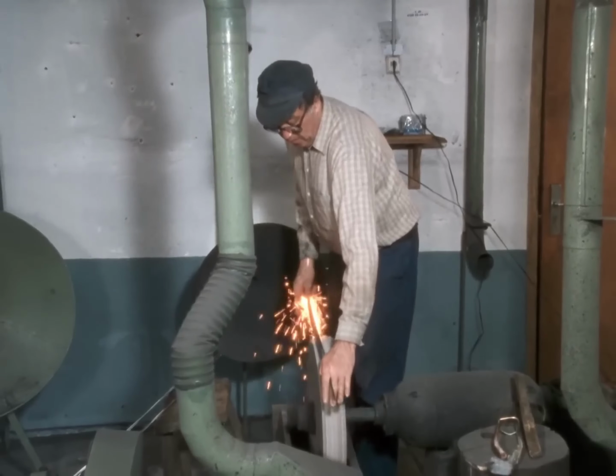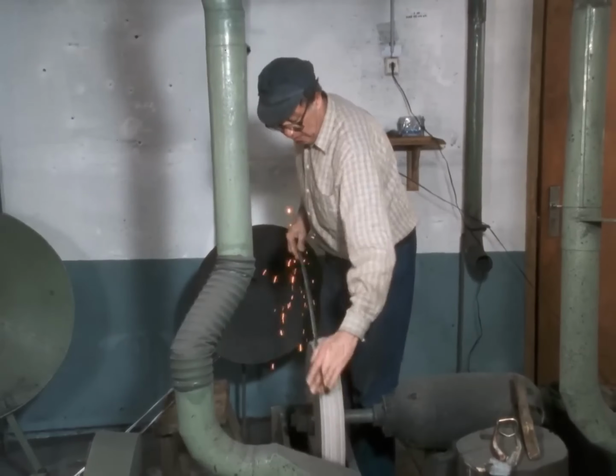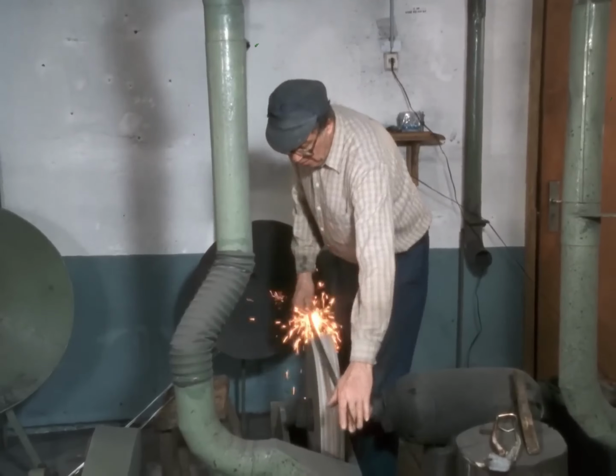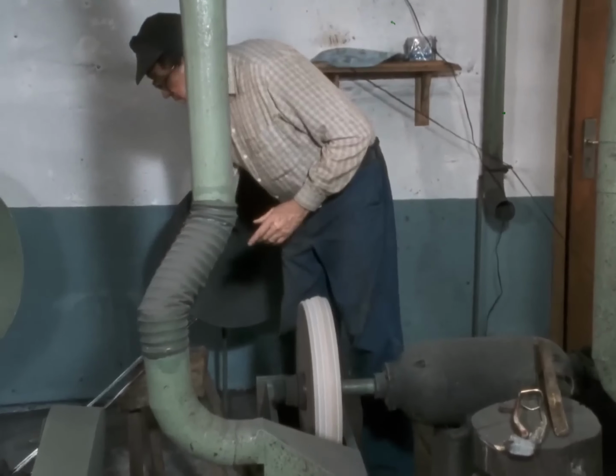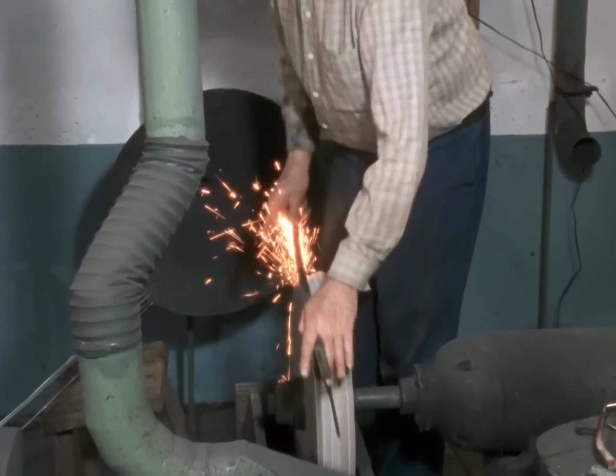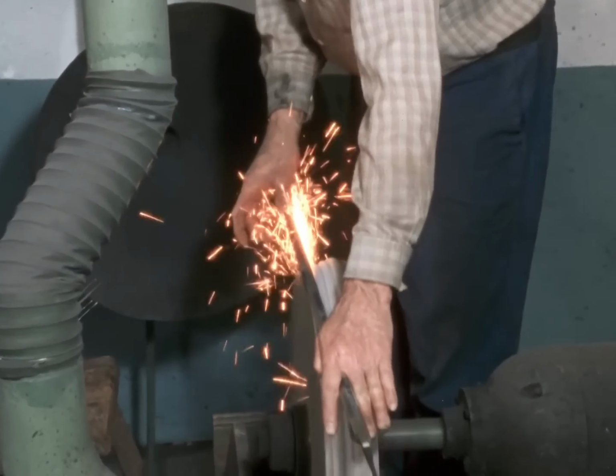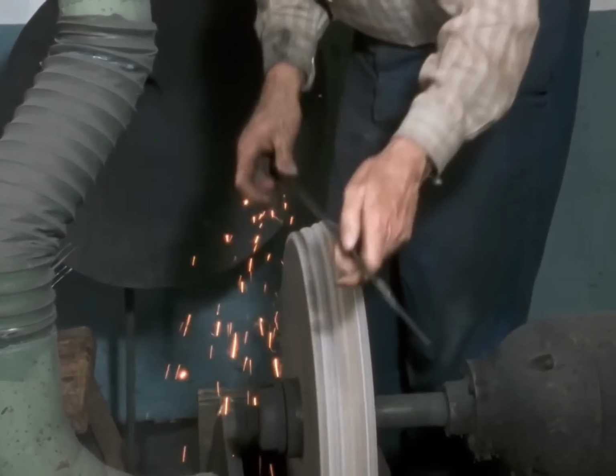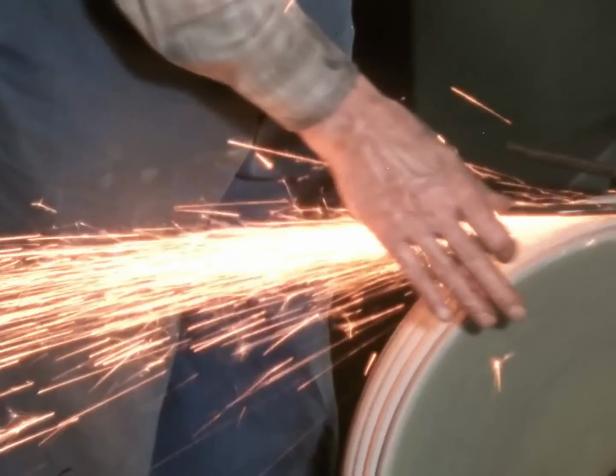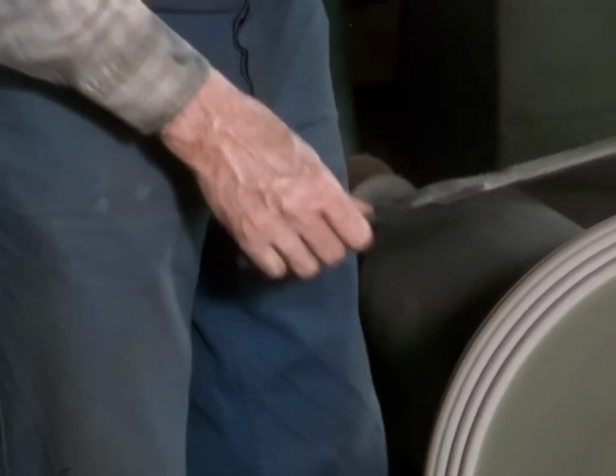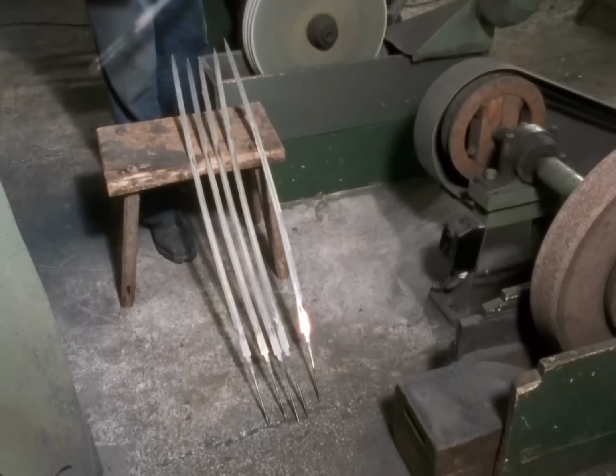Some grinding stones aren't flat at all. They're shaped, their surface ground into a matching profile that will cut the hollow groove into the blade rather than a flat face. This is form grinding, and it takes as much preparation on the stone itself as it does on the blade. On the thin, shaped wheel built for this cut, Ulrich slides the blade vertically along its length, sparks pouring off as the groove cuts deeper.